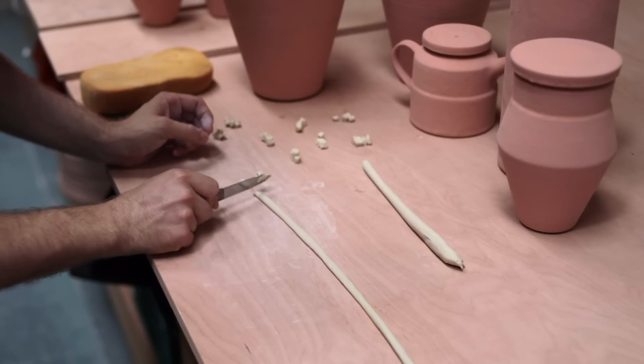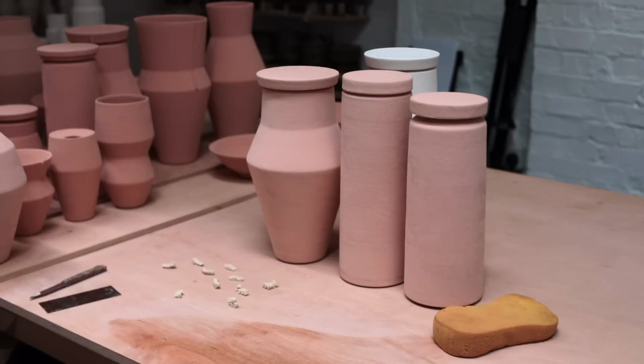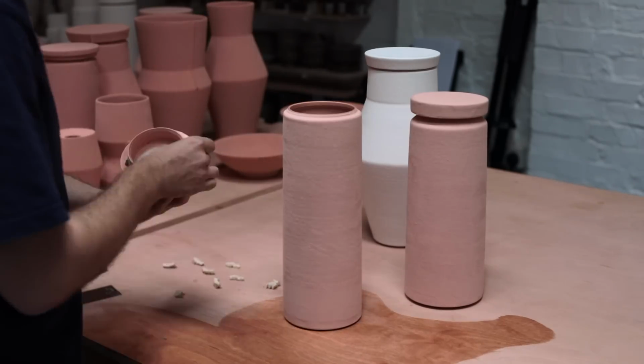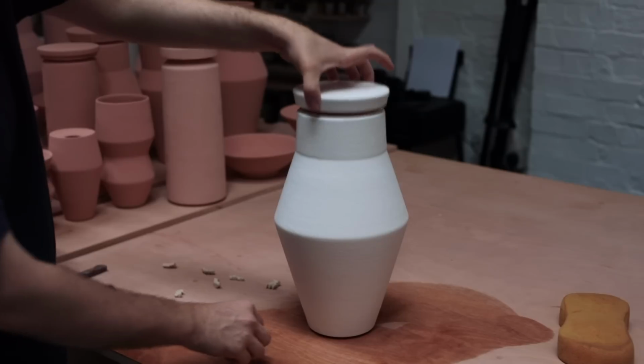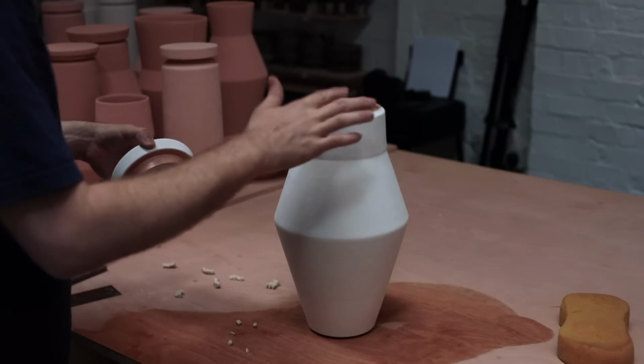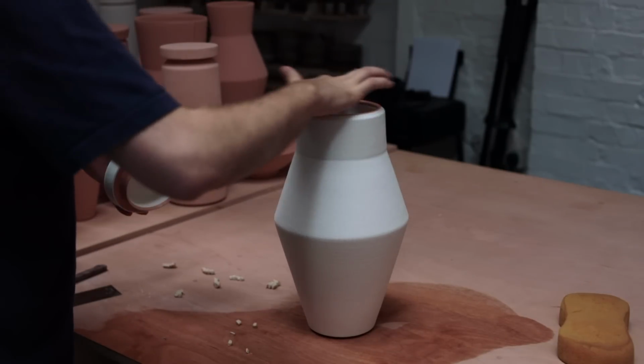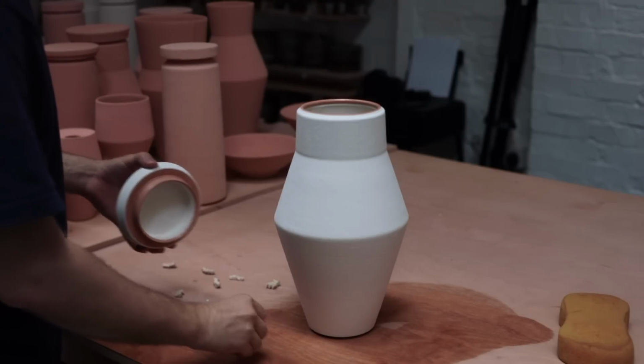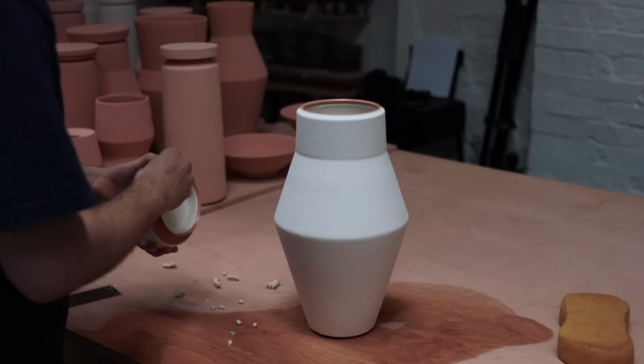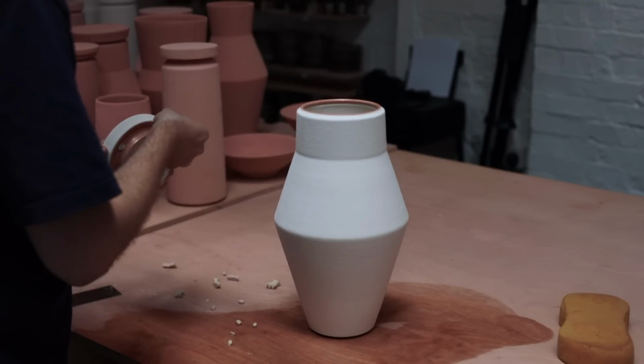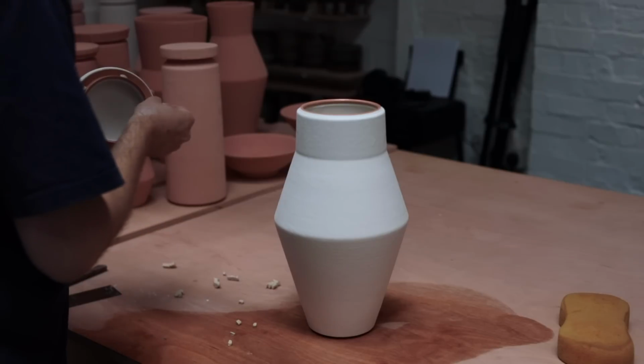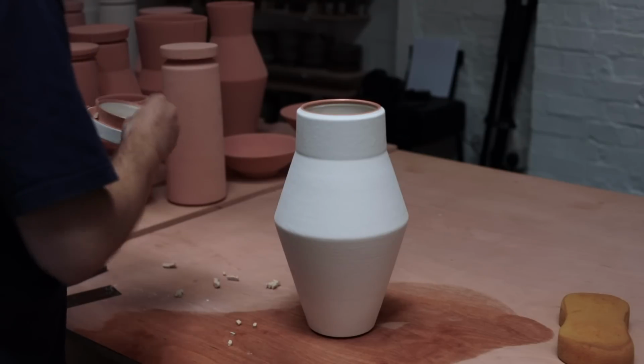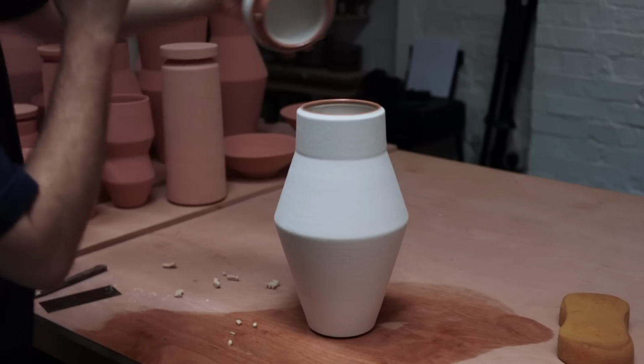This saves space, guarantees that the two parts will match one another, as sometimes in a reduction-fired kiln, the atmosphere can differ slightly in certain areas, resulting in different colours here and there. And when the lid is propped in place, it actually helps the rim of the jar to stay nice and round, as at such high temperatures there is a chance that pots can warp, especially their rims, if placed directly next to one of the burners inside the kiln.